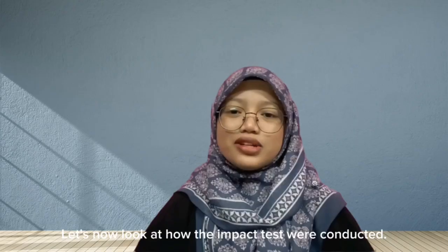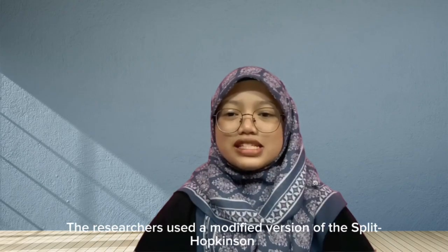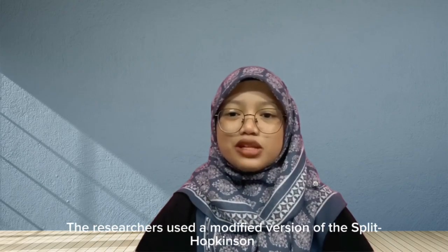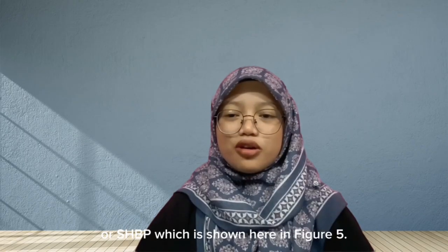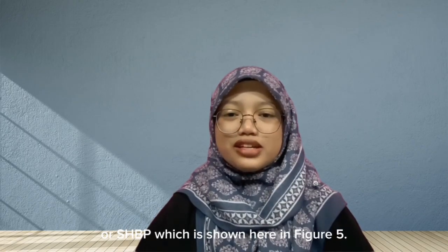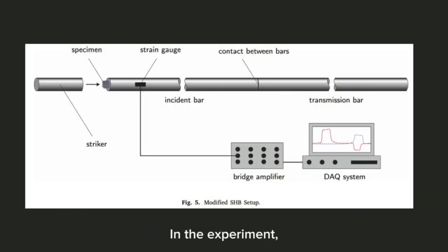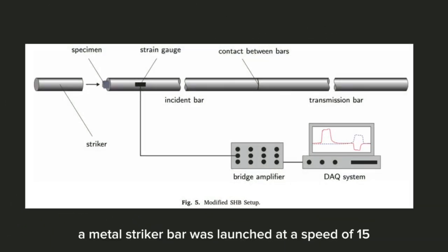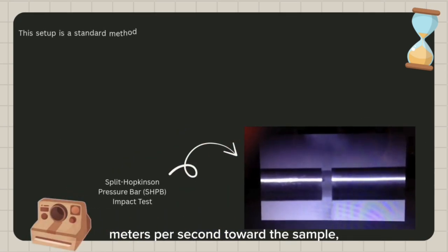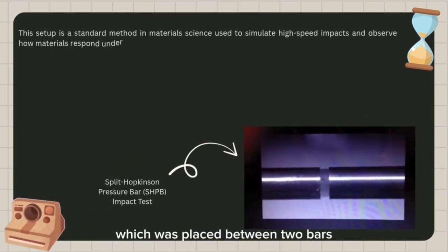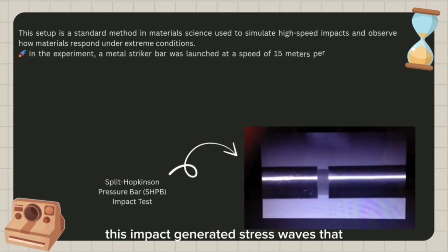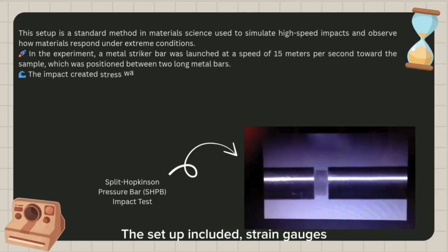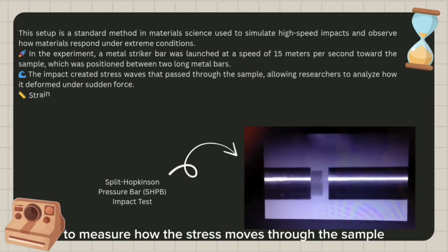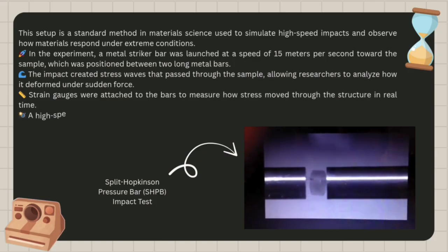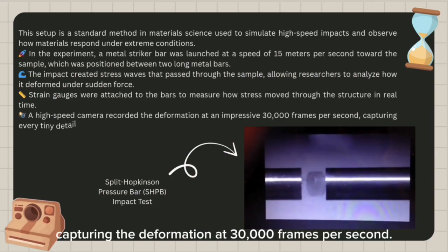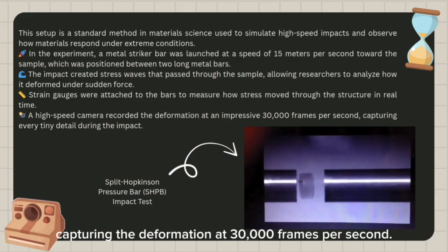Let's now look at how the impact tests were conducted. The researchers used a modified version of the split Hopkinson pressure bar, or SHPB, which is shown here in figure 5. In the experiment, a metal striker bar was launched at a speed of 15 meters per second toward the sample, which was placed between two bars. This impact generated stress waves that traveled through the sample. The setup included strain gauges to measure how the stress moves through the sample and a high-speed camera capturing the deformation at 30,000 frames per second.